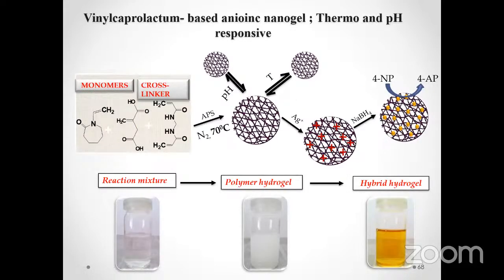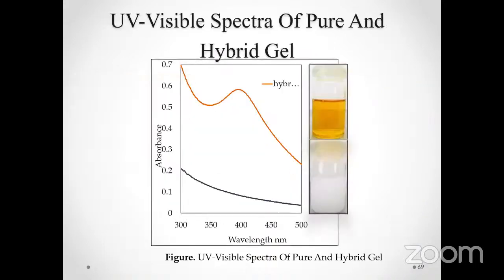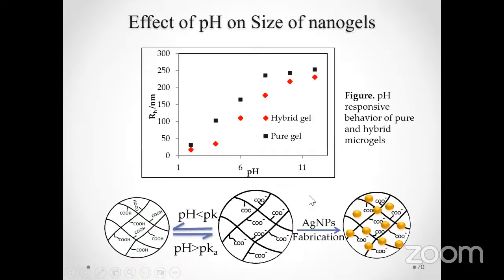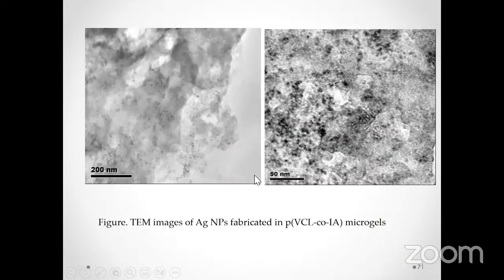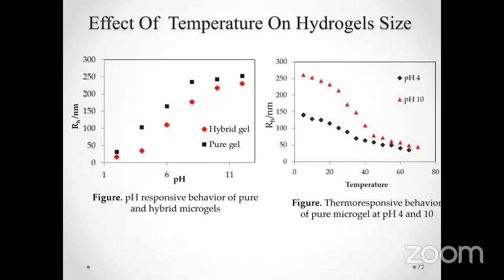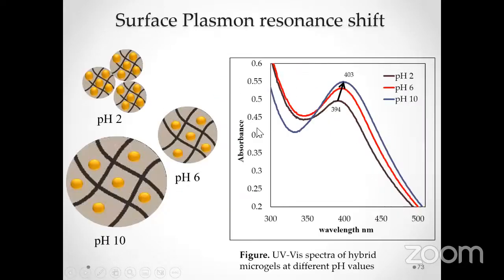Similarly, here is again the preparation of another thermoresponsive and pH responsive hydrogel, and then fabrication of the silver nanoparticles. And again, here is the optical response of the composite, where there was no optical response of the pure gel. And then this system was also temperature and pH sensitive. And of course, the TEM image shows the presence of silver nanoparticles, and here is the temperature and pH responsiveness of the hybrid systems containing the metal nanoparticles.